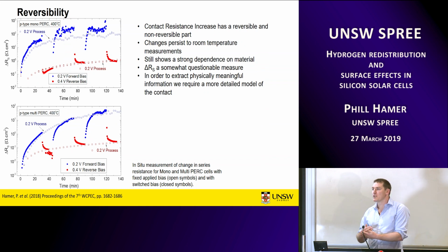So over time, when you get the really bad degradation, we can actually start to see the Schottky characteristics of the silver silicon interface start to appear. So we start to get a significant curve in the IV data, and what you end up then is having two diodes effectively back to back, hence why no current flows.